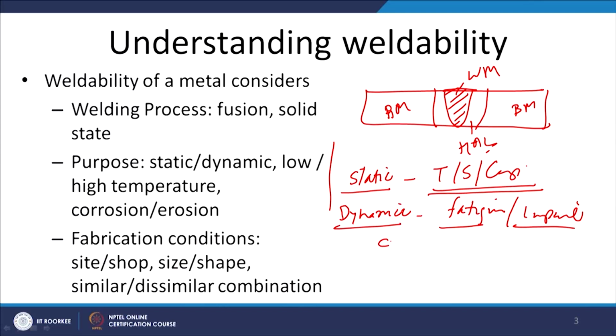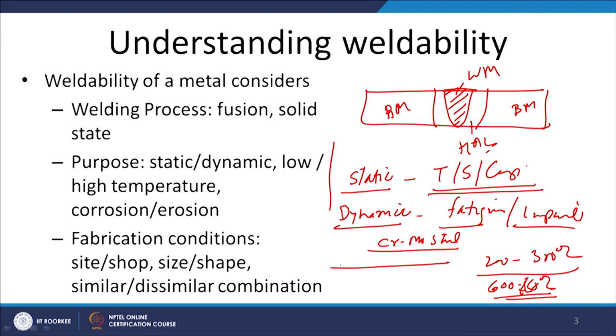For example, the joint of chromium molybdenum steel can perform successfully at 200-300 degrees centigrade without any difficulty. But when the same joint is operated at 600 to 650 degrees centigrade, the heat affected zone of such weld joints especially shows cracking. So, if the joint is developed, but it is not able to perform the intended function, then the weldability of the metal will be considered low.